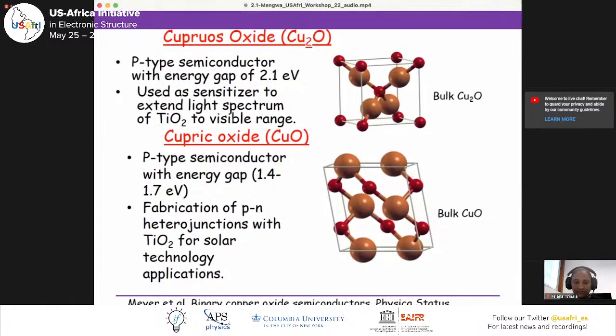The oxides that are usually coupled with TiO2 to improve its photocatalytic activity are the copper oxides. The cuprous oxide is a p-type semiconductor with an energy gap of 2.1 electron volts, and is used as a sensitizer to extend absorption to the visible range. The cuprous oxide has a cubic structure. The cupric oxide is also a p-type semiconductor whose energy gap ranges between 1.4 and 1.7 electron volts. It's usually used for fabrication of p-n heterojunctions for solar energy applications.